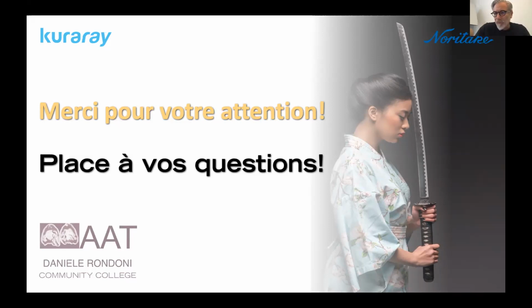But in that case, I use the porcelain to reproduce totally the color. Just in case I use the cutback and the portion is only vestibulary, it's not necessary for me to use the SBS, but for example, I use an internalized stain. And this kind of film of the internalized stain helps me to manage the color and to create the first link condition of ceramic in ceramic, because in internal stain there is also a portion of ceramic. Pay attention, the temperature in that case of the internal stain will be higher, 900 for 1 minute without vacuum. Ok, thank you.